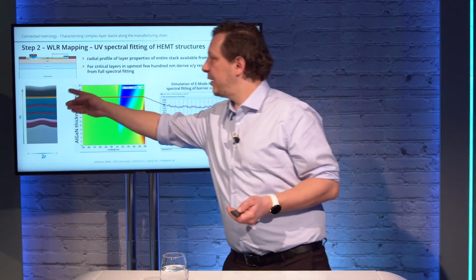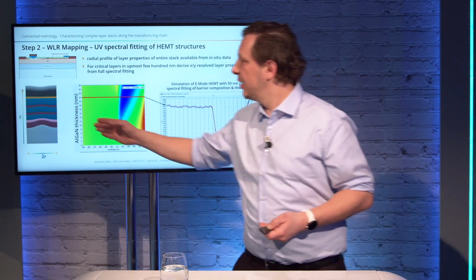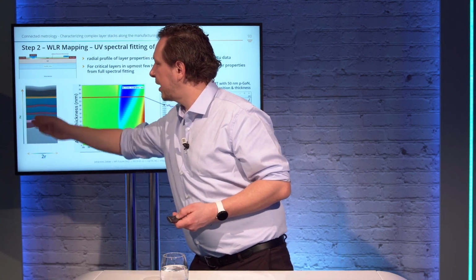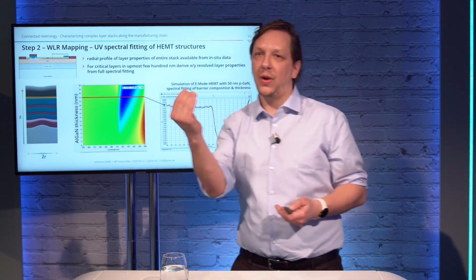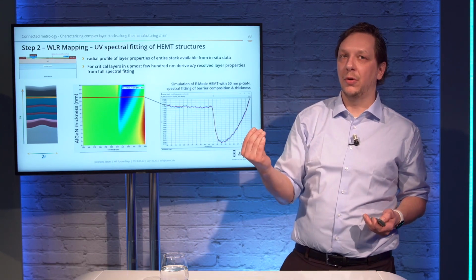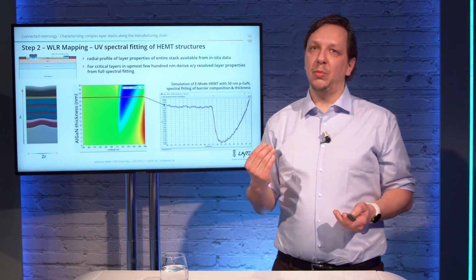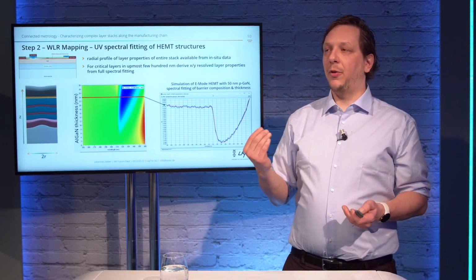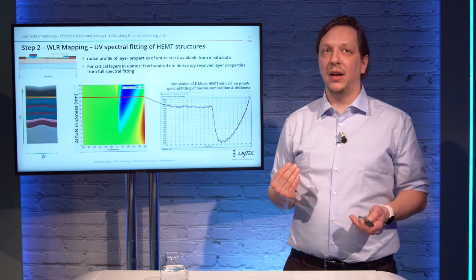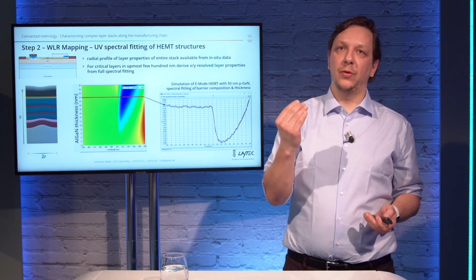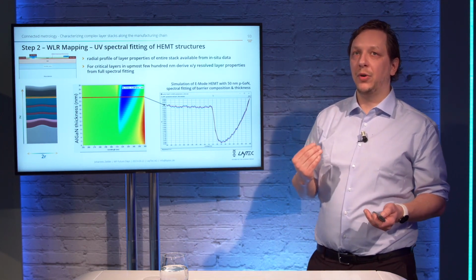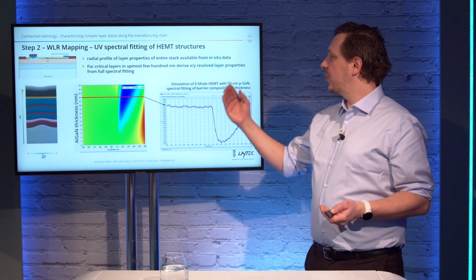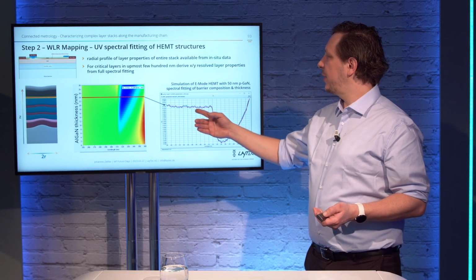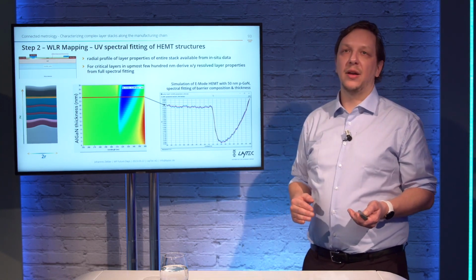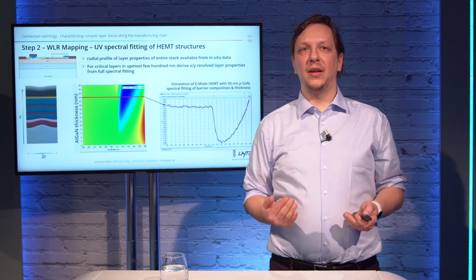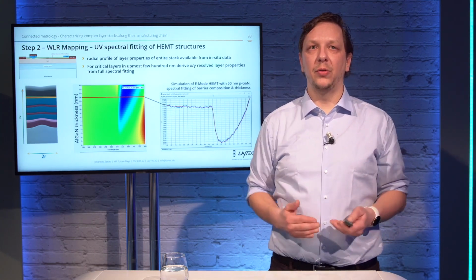But if we can take the data from in situ measurements, where we have already the depths, the Z information, so the stack information with R, so with the radius on the radial position on the wafer, we have a very good starting point for spectral fitting. And for non-critical layers, like for example the p-GaN layer, we can also decide that we do not need to fit this and just reduce the degrees of freedom. And thus we are able, for the critical layers, to do the spectral fitting. Here we see it for barrier composition and thickness, and just obtain these results on the 2D level.